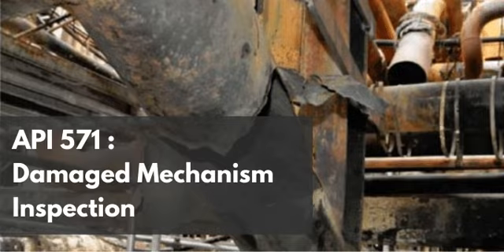This has been a massive journey. We've covered the underlying metallurgical theory. We've broken down why susceptible BCC ferritic structures, even expensive low-alloy steels, fail under chemical attack. We've explored the critical physical drivers of velocity and turbulence and the chemical driver of thermal degradation. We really unpacked it all. Yeah, we've pinpointed the massive risk to the welds in the MEA reboiler to regenerator piping, unpacked the terrifying UT inspection paradox where corrosion mimics a crack, and detailed the strict operational controls required to prevent the whole disaster. It truly is a densely interconnected mechanism. It is a place where fundamental chemistry, complex fluid dynamics, metallurgy, and daily plant operations all intersect and collide at a single, vulnerable weld seam.